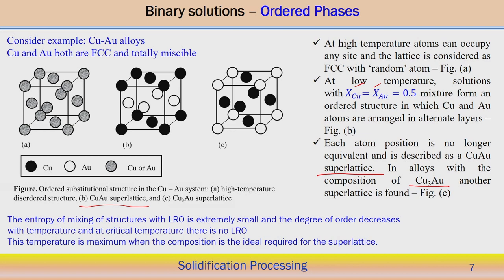In the ordered structure — ordered phases — when a binary solution is made, depending upon the temperature, it can create a very disordered structure or ordered phases at a particular temperature, specifically at low temperature, creating different ordered structures. This order can be followed layer by layer or in some other atomic arrangement to create a super lattice — either CuAu or Cu3Au. The entropy of mixing of the structure with long range order is extremely small, and the degree of order decreases with temperature.